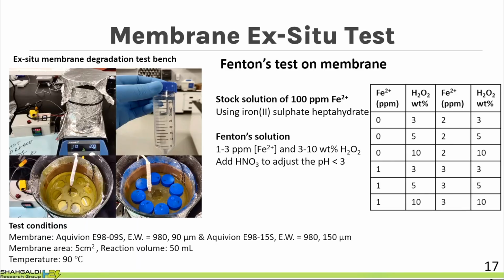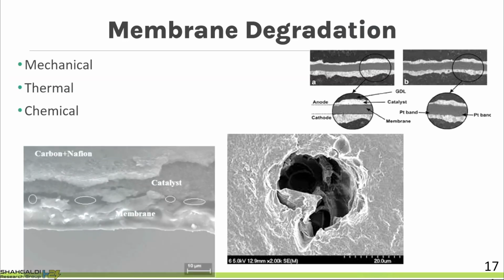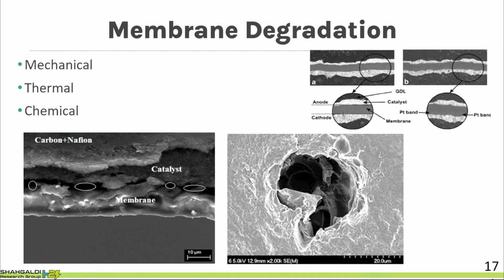So, we also do a lot of ex situ tests when we receive the membrane from industry, before we move forward to the in situ test in the stack. Imagine that we have different components inside our fuel cell and electrolyzer. If we have a material that somehow accelerates the Fenton reaction, we may accelerate the degradation of the membrane inside the cell. It means that we have pinholes, or we have thinning of the membrane. So definitely we need to have the ex situ test before we move forward if we are developing the ionomer.